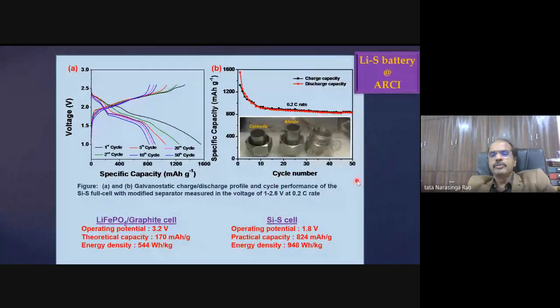And you can see 50 cycles at 800, whereas usually 200, or 170, is for the conventional battery material, and I'm talking about 800 with very good stability. We tested up to 50 cycles, but the trend seems to go beyond that. So practically, the energy density can go up 2 times, 3 times, because you put a lot of carbon as support, but that itself is a good achievement.